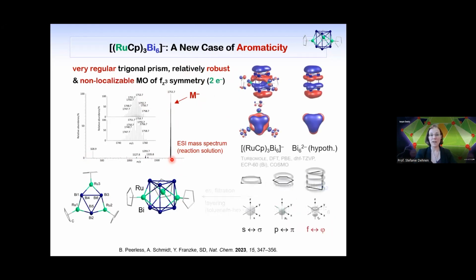And then if you check and analyze the molecular orbitals, you will find a very interesting molecular orbital that looks exactly like an orbital that you calculate for a hypothetic bismuth 6,2- cluster. So this is not known experimentally, but you can compare and see it's exactly the same. And now we come to symmetry. So this is an s orbital and a sigma symmetry of a molecular orbital. Here you have a p atomic orbital and a pi symmetry of a molecular orbital.